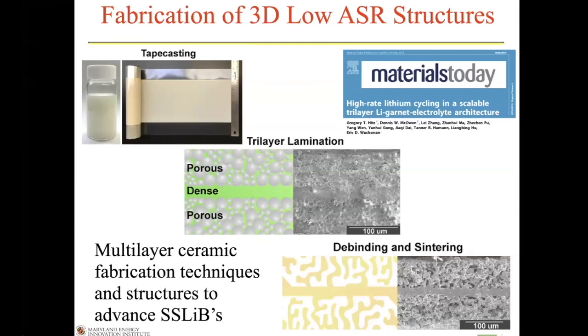And this is done by very conventional ceramic processing called tape casting. We just mix the powder in appropriate solvents and binders. We cast them on a sheet. We laminate three layers in this case, with a dense layer in the center. On the outer two layers, we put a pore former, just a polymer bead, which burns off in the furnace. We put them into a furnace in one step and we get the structure in the lower right.